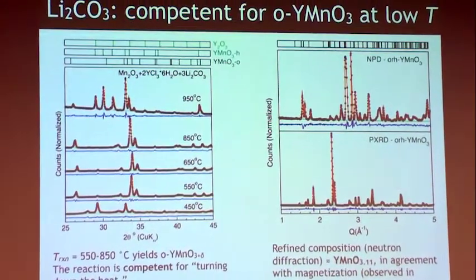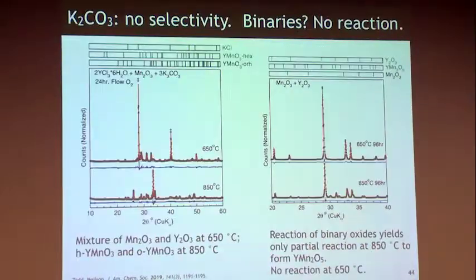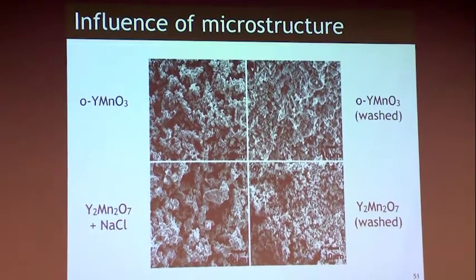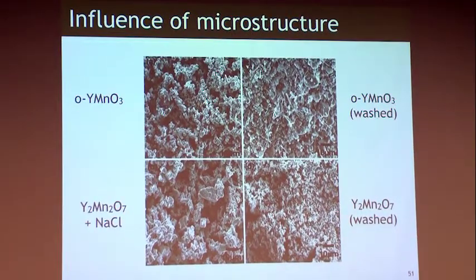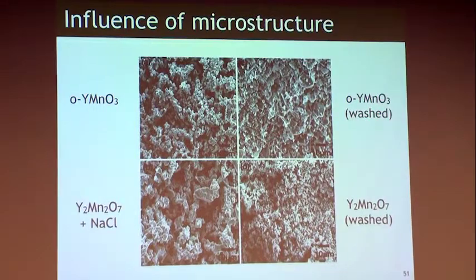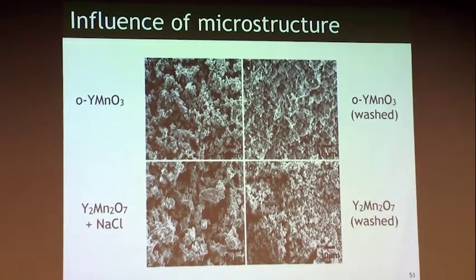Right, so I think for this particular example, at lower temperatures, they're certainly less crystalline, but they are reasonably crystalline. I do know the size dimensions. I think I put that in here. Yeah, there we go. If you just look with scanning electron microscopy on that perovskite phase, this is the washed material, we're getting to about micron particle sizes.